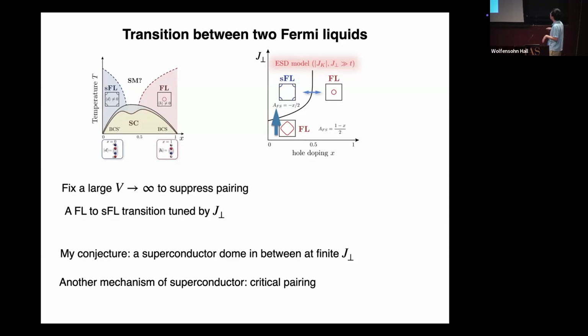Then at a fixed x, we tune J-perp. At a large J-perp, it's this model, so we know it's this small Fermi liquid. But at a small J-perp, we still expect a large Fermi surface with area 1 minus x/2. So the question is, when I increase this Fermi interaction, how does this transition happen? So this is a very hard question. I don't really know the answer, but I will show you a conjecture. There is a superconductor dome in between at zero temperature.